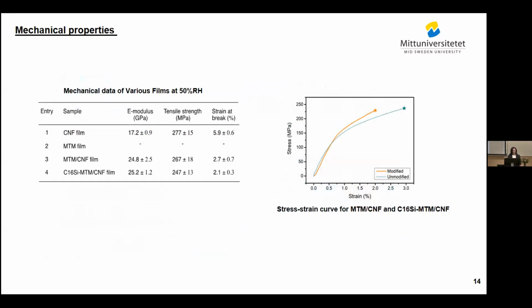We measured the mechanical property of the MTM-CNF before modification and also after modification. We see that here we increase the Young modulus when we have MTM in the nanocomposite from 17 to 24. But the aim of this work was to prepare a hydrophobic material without disturbing or destroying the mechanical property and the structure. Okay, then the data after modification, this modulus, show that we didn't change the mechanical property, and the structure of the MTM-CNF brick and mortar structure is preserved during the modification.